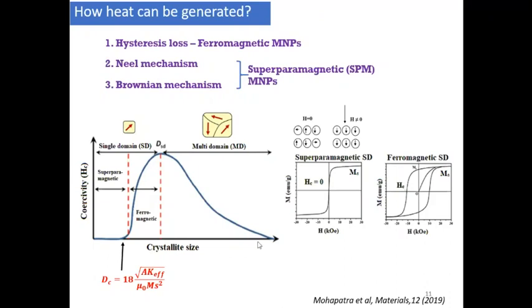We can look at the coercivity versus the crystallite size of the materials. Initially in the bulk, it is a multi-domain region. When you decrease the size to a particular size, it is still in the multi-domain region, but the coercivity is quite high. When we have coercivity, it means it will develop permanent dipoles. And we are employing an AC magnetic field for the generation of heat, because we have to go through several cycles.